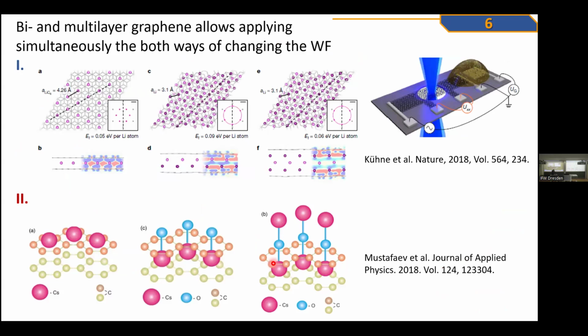Firstly, it can be intercalated with atoms, for example, alkali metals, which enables the mechanism associated with the Fermi level shift. Secondly, there is the idea of polar atomic complexes, for example, of alkali metal and oxygen atoms, which can be fixed between the layers of bilayer graphene and reduce the work function due to surface dipole formation. Such a variant is known in the literature, but our investigation has shown that it is not realized.